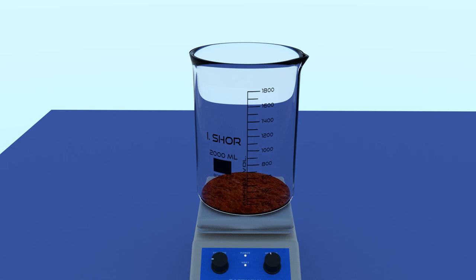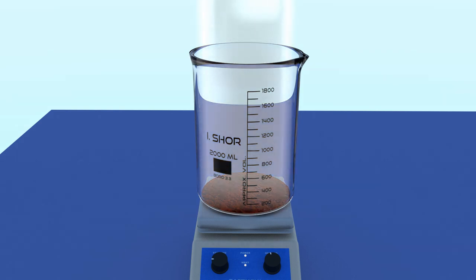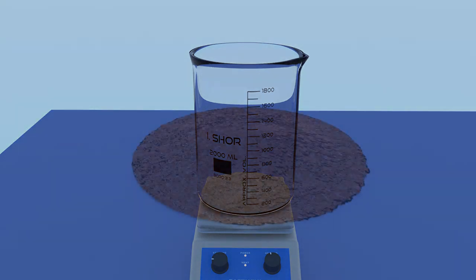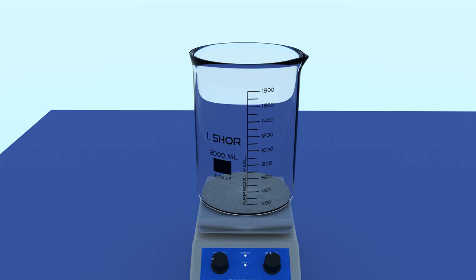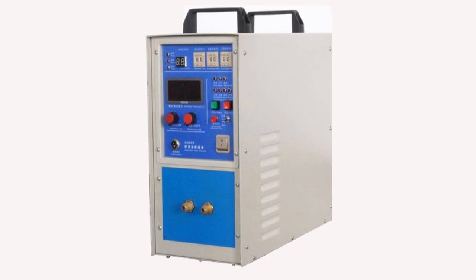As the platinum chloride dries, white smoke, steam, is generated. Once the chloride is dry, the smoke will turn yellow or brown, indicating that the chloride is being driven off, leaving pure platinum powder. This step is critical. Any attempt to melt the platinum while it is still a chloride will simply vaporize the platinum. Once the colored smoke is no longer being generated, you can melt the platinum. Melting platinum powder is most easily done in an induction furnace.